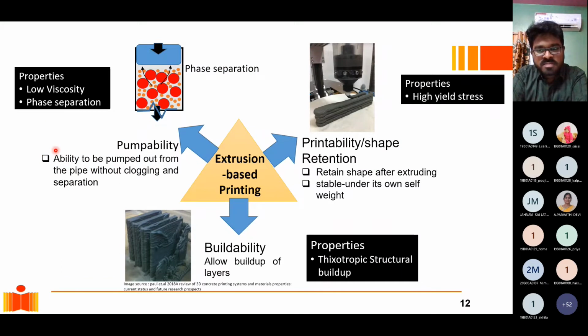Of course, this requires understanding the material's behavior. If you look at extrusion-based printing, the first requirement is pumpability. This is a suspension, with aggregate in the binder paste. When I pressurize it, I should not have any phase separation, so water and other lighter materials should not get squeezed out. Then it should have printability and shape retention, keeping its shape as it comes out of the nozzle, and buildability. You see what happens when I don't have buildability: as I stack layers, I can have collapse. Whereas with a good buildable mix, I can stack layers and build the structure up one layer at a time.